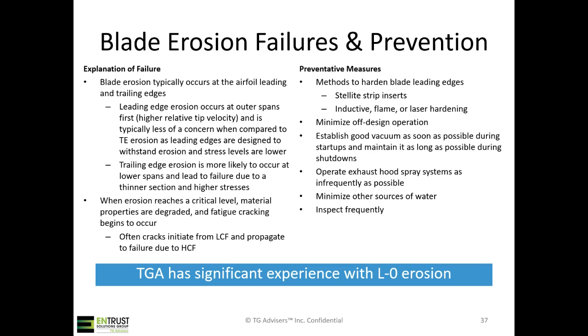So there's a few different concerns. Obviously, erosion is a very rough surface, so there's concern over cracks initiating from the eroded area. But then you could also potentially lose enough mass that you change the mass of your airfoil and change the natural frequency of the blade. So a blade that was well designed could then potentially lose enough mass to start having excitation and vibration problems.